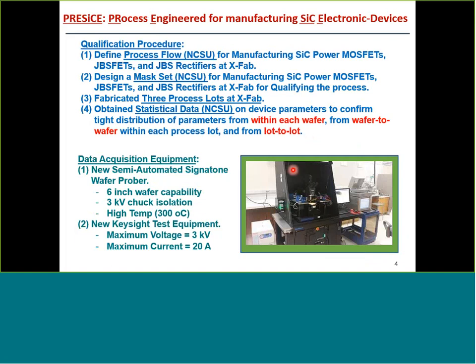So in terms of the PRESiCE process, we have spent a lot of effort to qualify the process by defining a process flow at NCSU to manufacture silicon carbide MOSFETs, JBS-FETs, and JBS rectifiers at X-FAB. We designed a mask set for this purpose and provided it to X-FAB, and they ran 3 process lots for the qualification. The wafers came back to NC State, and we did extensive testing to get statistical data, and I'll be showing you wafer maps and statistical distributions.